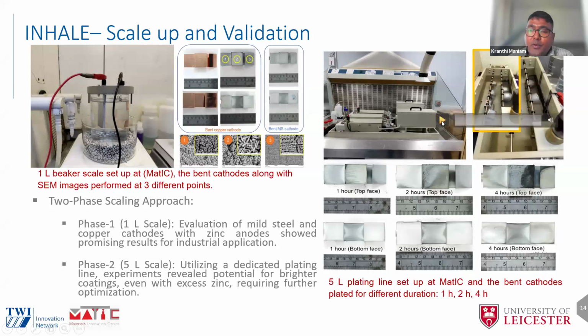I would like to show you a video where you can see the plating happening in the 5 liter tank, and you can see how well it is plating. You can see the coverage happening on the top face and on the bottom face, meaning that you have a good coverage, and the efficiency of the electrolyte is good, and it can cover all the surfaces for a given current density and temperature.